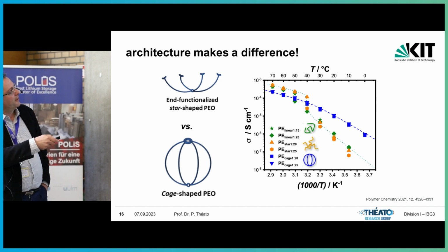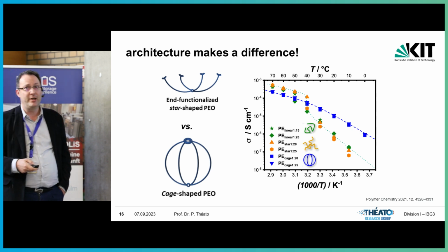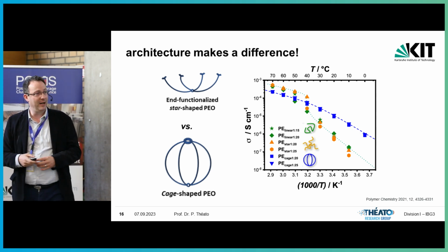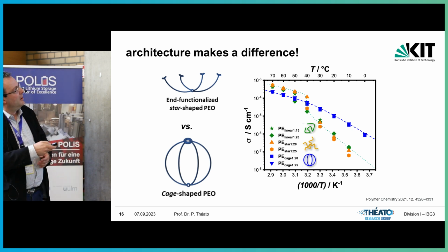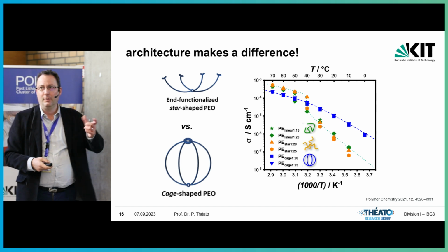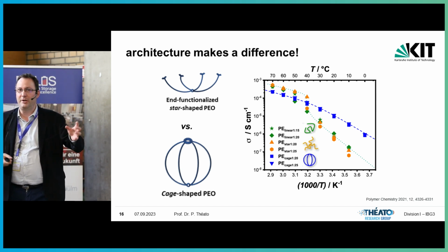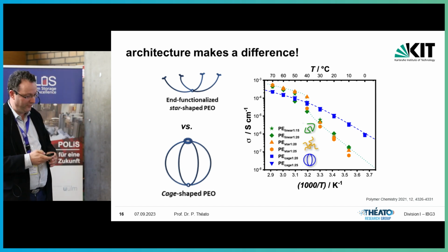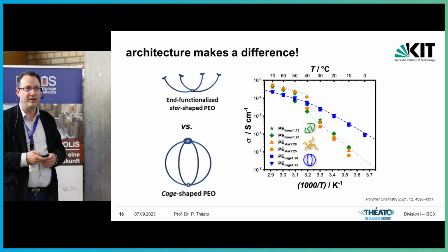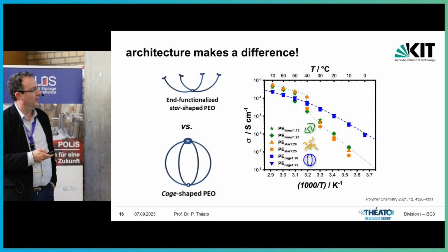But as soon as you form the cage, you can see that in the blue data you get here, okay? There is no crystallization taking place anymore. That obviously has to do with the architecture. But the conductivity is lower for the higher temperature parts. So this is what I really think is the difference on, you know, the forbidden part that you cannot make a helical structure maybe. Well, that's something interesting to look at, but I will send samples to Vito and then he can figure that one out for us. And that would be pretty interesting.